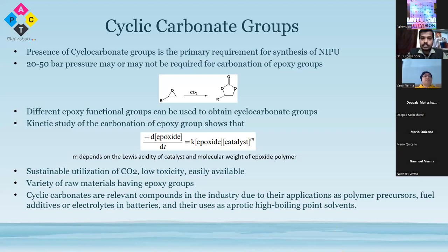he has worked a lot on these non-isocyanate polyurethanes. He has conducted all his experiments at room temperature and atmospheric pressure of carbon dioxide. So I just use that method only. Different epoxy functional groups can be used to obtain cyclic carbonate groups, and the kinetic study of carbonation of epoxy groups shows that the rate of reaction is directly proportional to the concentration of epoxy group as well as the catalyst. So it is a sustainable utilization of CO2 as discussed, low toxicity and easily available, because carbon dioxide is a cheap material.